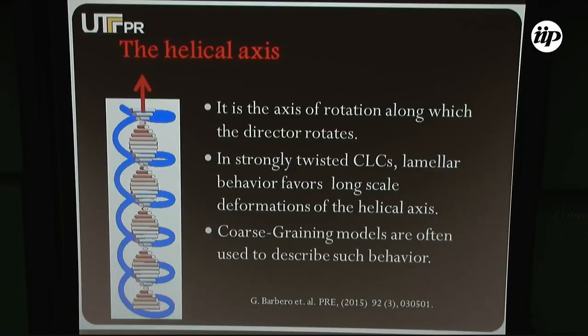In most of the cases, I'm going to say here, we're going to talk about strongly twisted materials, which means the pitch length is much smaller than the cell you are using. So we call it strongly twisted. In this situation, you can consider it as a lamellar behavior, which means it costs energy to change the pitch. So instead, you can just think of a smectic-like behavior where you can just change this helical axis direction. And I'm going to show here that it makes a big difference if you can orient this somehow for several applications.